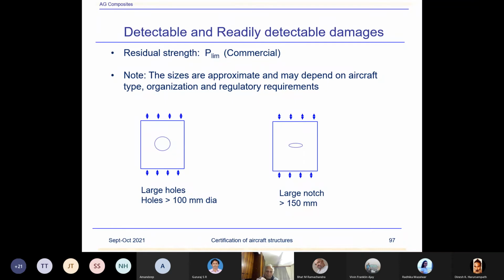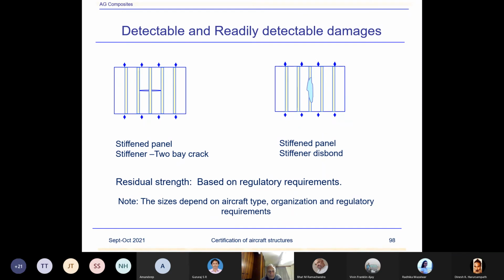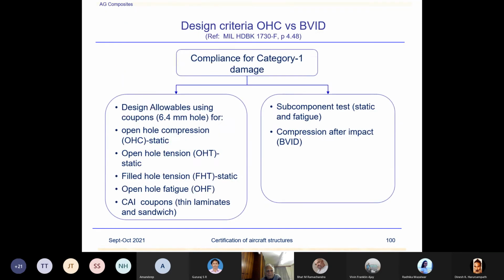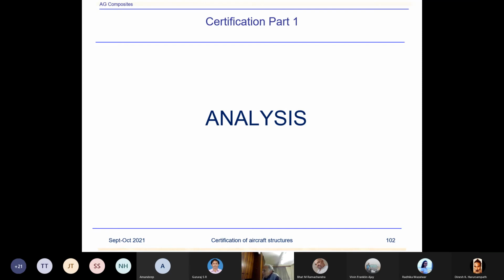Another issue with repairs is, and we define that, if the repair fails during service, then the residual strength capability of the damage has to be retained to the limit load carrying capability. So there are a lot of issues when we define the repair. They're not easy. Repair sizes, we design them, and the type of repairs. A lot of analysis and testing goes in when repair manuals are prepared by the company. It's a big task. It's not simple. Okay, so readily detectable damages, we have defined those. Any other question before I move from here? No.